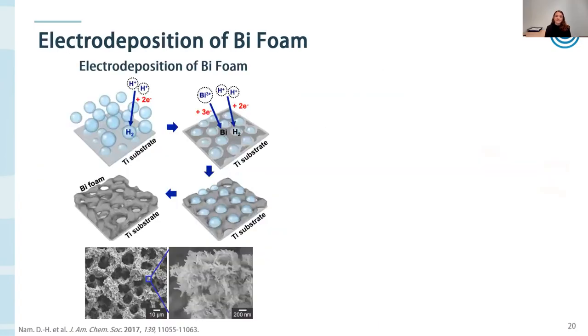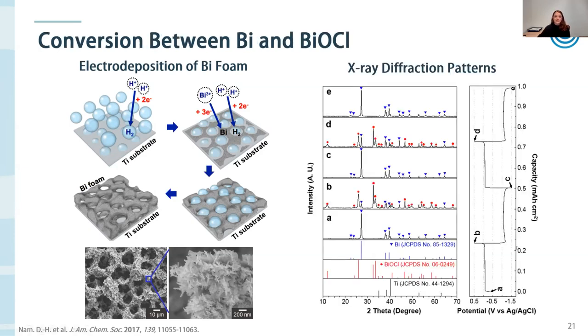When we first started testing bismuth as an electrode material, Jawan had the idea to develop an electrode deposition method to produce these high surface area bismuth foam structures to try to maximize our salt removal capabilities. And the first thing that we had to do is characterize our material to see if we're actually doing the reaction that we wanted to do.